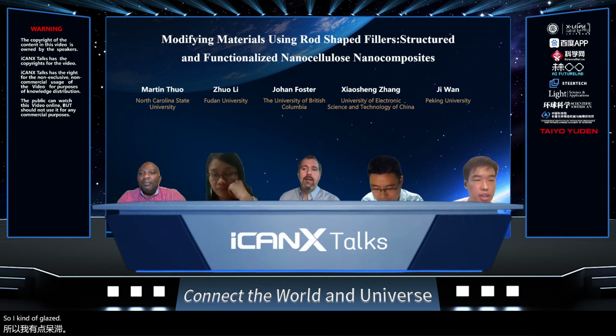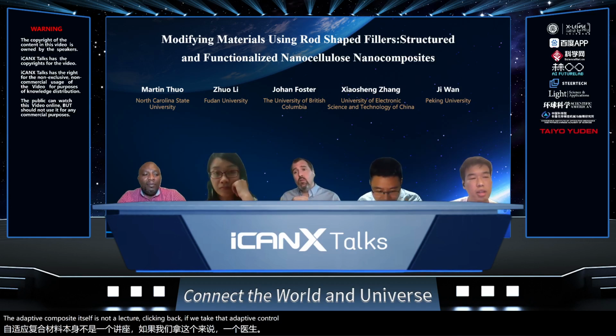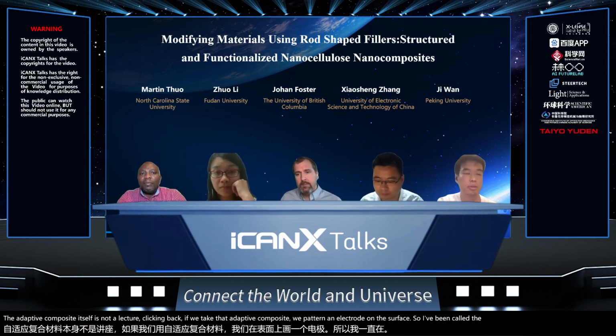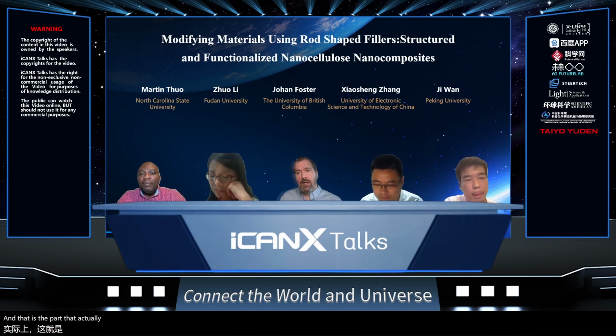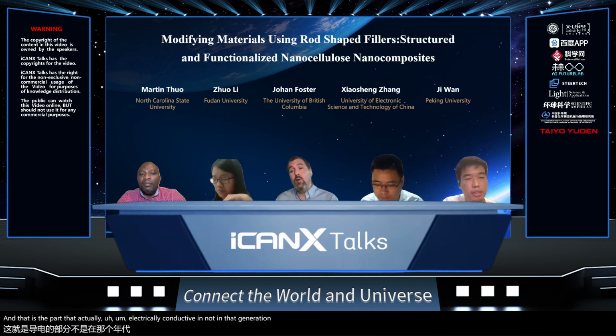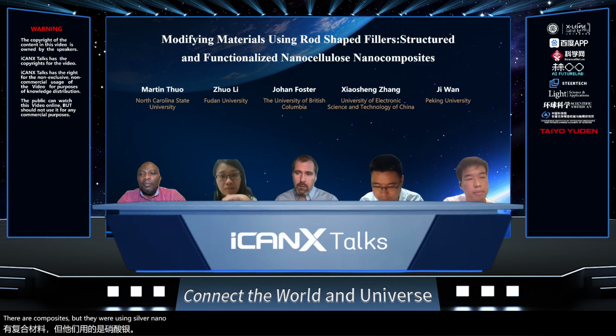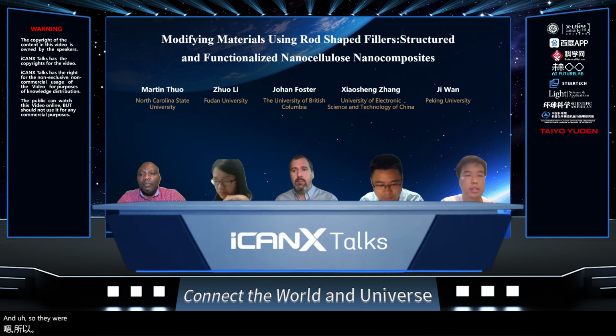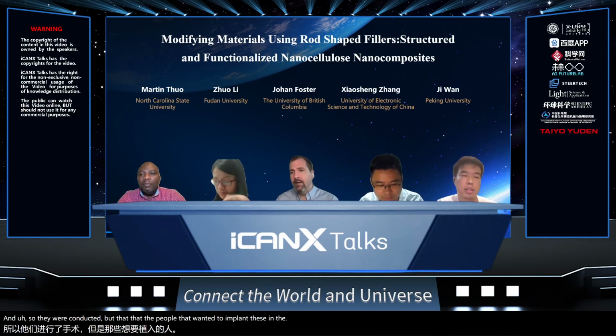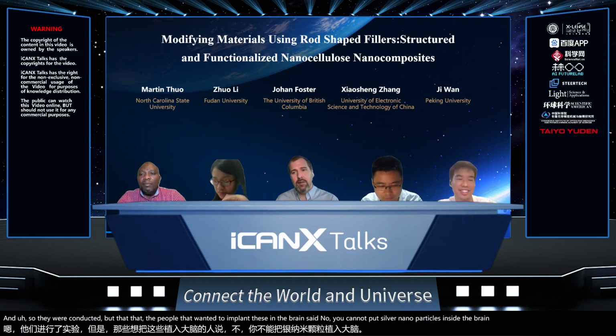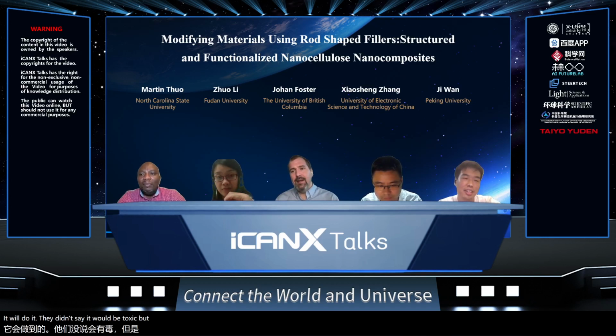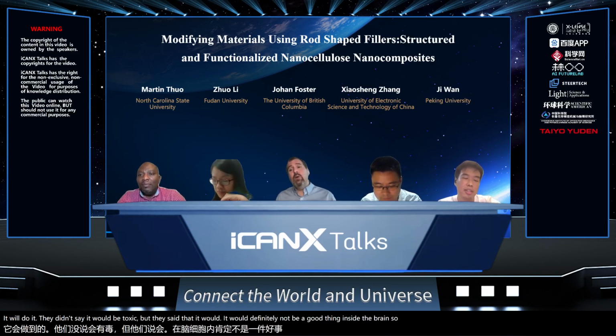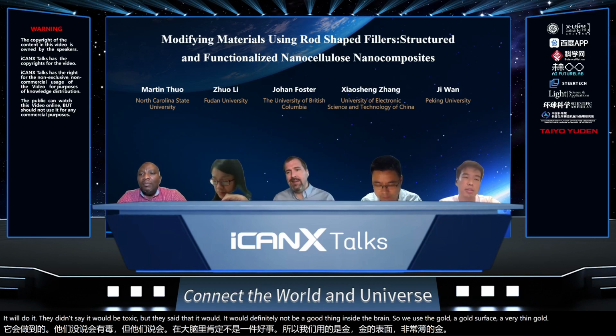So I kind of glazed over that. The adaptive composite itself is not electrically conductive. We take that adaptive composite, we pattern an electrode on the surface, so a thin gold electrode. And that is the part that's actually electrically conductive in that generation. We have made electrically conductive composites, but they were using silver nanoparticles, and so they were conductive. But the people that wanted to implant these in the brain said, no, you cannot put silver nanoparticles inside the brain. They didn't say it would be toxic, but they said it would definitely not be a good thing inside the brain. So yeah, we used a gold surface, a very thin gold electrode that didn't affect the mechanical properties. Yeah, okay, thank you.